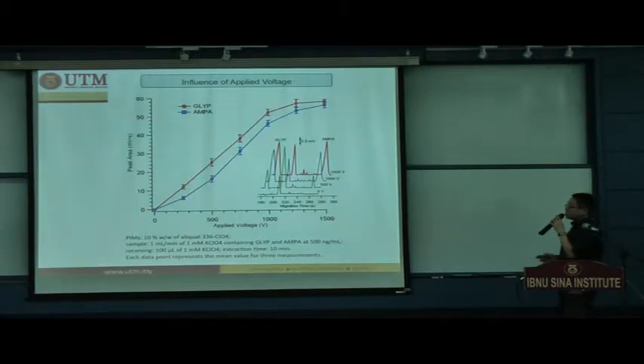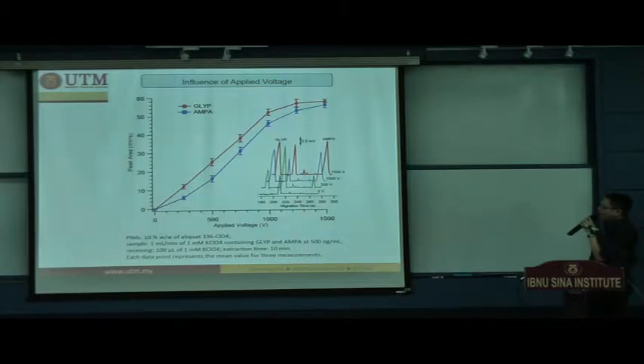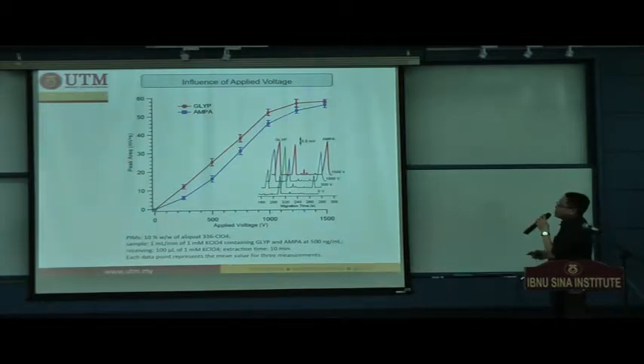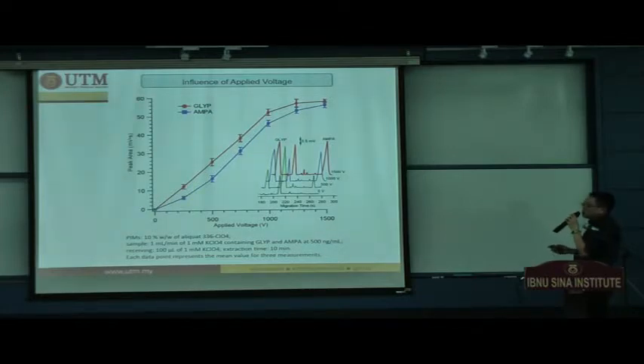So this is a graph showing the influence of the applied voltage. If you apply only 0 volts, by turning on the pump to pump the samples but applying no voltage, basically there is nothing that you will see in the acceptor solutions. But the amounts of the glyphosate and AMPA detected in the acceptor solutions increase tremendously together with the increase of the applied voltage. And eventually it reaches an equilibrium state, when the applied voltage is above 1000 volts.